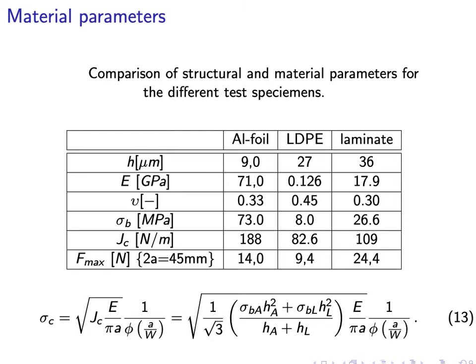On this slide you see the data for the aluminium foil, the polymer and the laminate. All of them are measured quantities, and for instance the critical energy release rate, the J, was taken from experiments and also proven to be very well represented by the contributions from the aluminium foil and the polymer, when the laminate was produced and measured, with an accuracy within 10% or even less than that. Maximum force is also well predicted just by using a cohesive zone model and finite elements.